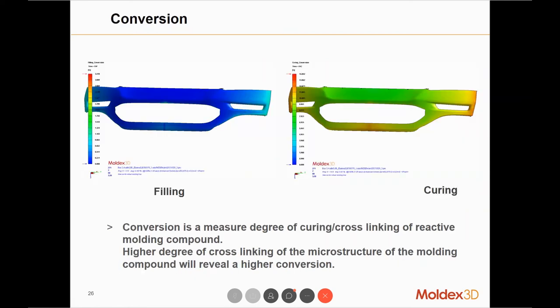And then one of the most important results for thermoset material is the conversion, the curing rate. During the filling stage, if the part is being filled at a very slow speed, we might have a higher curing conversion rate. And that means we'll have a higher viscosity. With a higher viscosity, we'll have a higher injection pressure, and sometimes in some very thin region, we might even have short shot if the viscosity is too high.